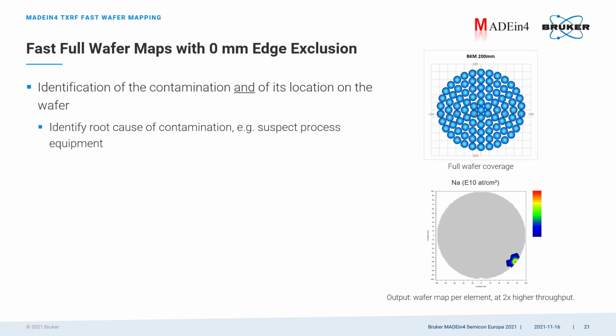The beauty of TXRF is that it is a non-destructive method and it is possible to measure full wafer maps that show you where on the wafer the contamination is located. I put an example of a map of sodium on the right hand side. As you can see, the tool is sensitive to the very wafer edge.